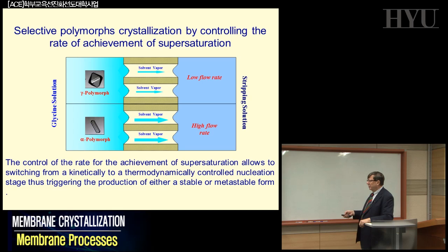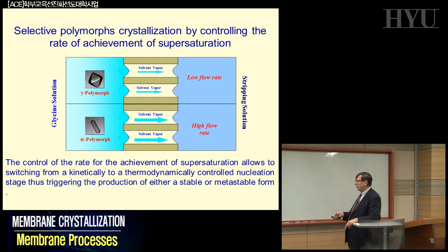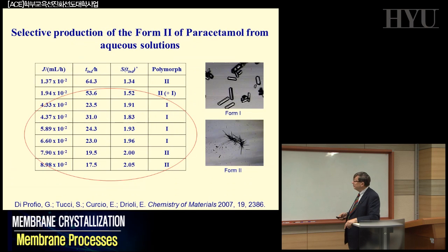Quite interesting. So the control of the rate for the achievement of supersaturation allows switching from a kinetically to a thermodynamically controlled nucleation stage, triggering the production of either a stable or metastable form. What is happening here? By the way, this is the same story that I was mentioning before of paracetamol. You can see here the same kind of phenomena. You can have form 1, form 2, depending on the different parameters characterizing your normal membrane operation, which we are used to affect.